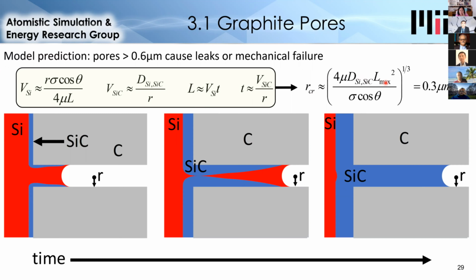So setting that to 10 millimeters, which is thinner than the overall tank wall in the full system, which is about 100 millimeters, we find that the critical radius is estimated to be around 0.3 microns, or 0.6 micron diameter. So considering the rough order of magnitude of these equations, we estimate that a critical pore size based on diameter would be about 1 micron.